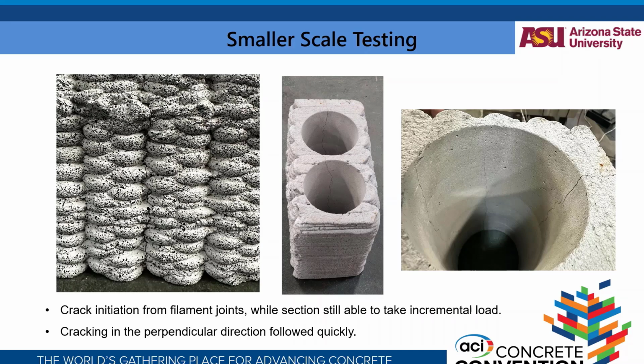There's a crack over here that is not as visible because it coincides with the joints. So the crack initially started with these joints cracking first, while the section could still take significant load, most probably because of the stable section. It was a larger stable section, and then the crack propagated in the perpendicular direction. So this is the interlayer joint direction. There are cracks in the interlayer joint directions also, and later on the two cracks are in the perpendicular direction.